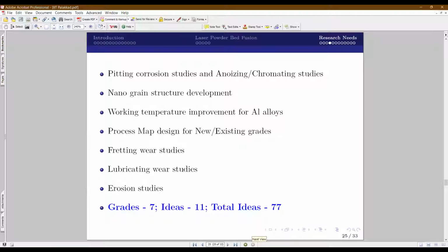And developing nano grain structures is possible through 3D printing. There are some reports already available by some German researchers. So those are areas you can think of. Currently aluminum alloys are used up to 120 degrees Celsius. By using Scalmalloy or RAM 10, it is proposed that the working temperature of aluminum alloys can be increased to 200 degrees Celsius. So you can channelize your work on how to identify the grade and the heat treatment which can help you use this material in a much higher temperature environment like 200 or 250.